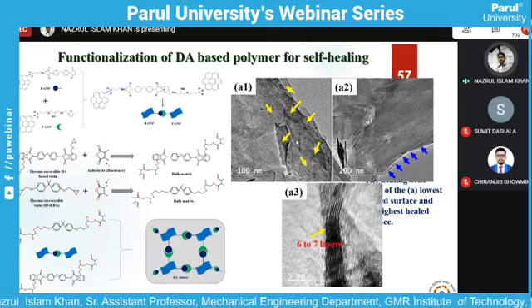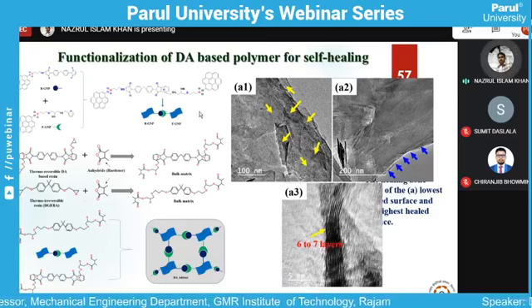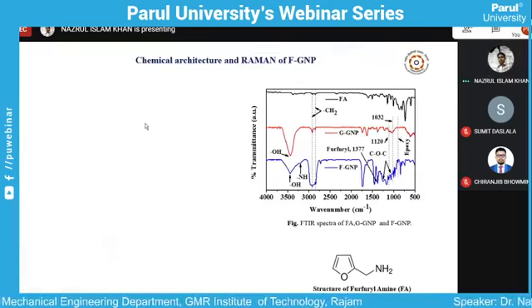For that we functionalized the graphene with this bismaleimide. To add bismaleimide, first we needed to functionalize with the amine group and epoxy group, and finally we were successfully able to add this bismaleimide, and that's why I have shown the functional groups.